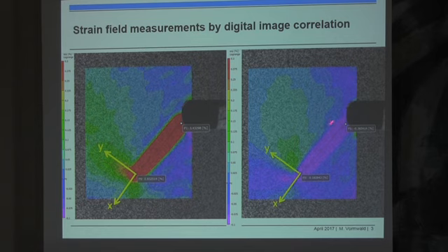On the right-hand side, the shear tensor components, epsilon xy, are plotted here for the same instant as on the left-hand side. We collected such data during cycles. There have been many cycles without data collection, and after 500 or 1,000 or so cycles, we introduced 3 cycles with measuring. And just to give you an impression how it looks like,